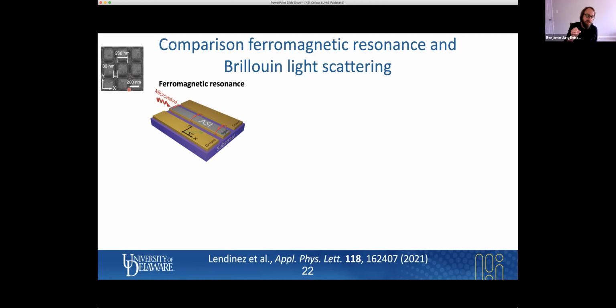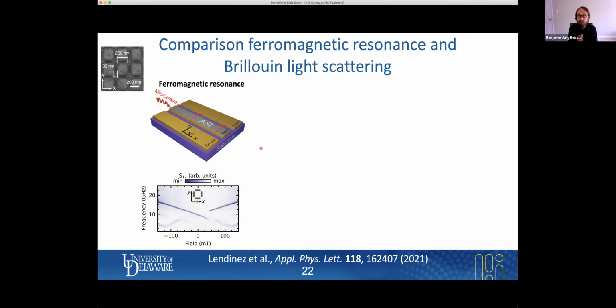Now, how do we perform the measurement? We send the microwave signal in and measure the transmission, detect this with a vector network analyzer, and we get one frequency trace, the signal as a function of the frequency, the absorption as a function of frequency. We can now do this for each field step, and what we get is a color-coded image, as you can see here. So we have here frequency versus field, and the color represents the S12 parameter. So that's the transmission parameter. The stark contrast means we effectively excite dynamics in the system, so we have a strong absorption.